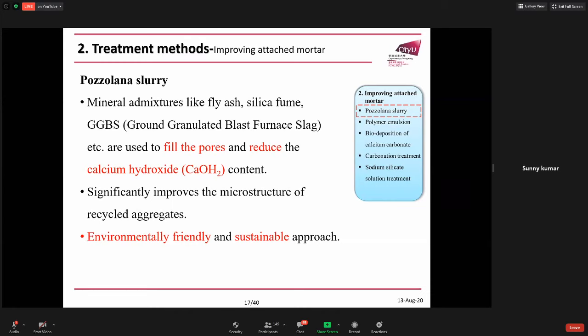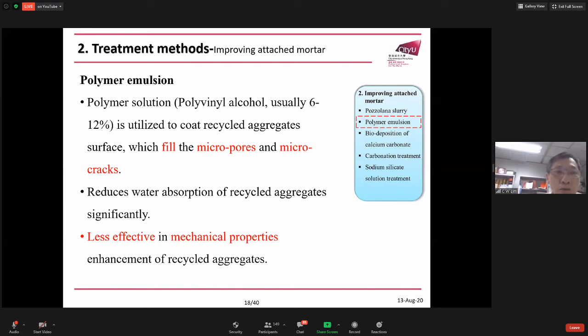The other treatment method is by improving the attached mortar. The first one is the pozzolanic slurry. Mineral admixtures like fly ash, silica fume, and GGBS are used to fill the pores and to reduce the calcium hydroxide content. It will significantly improve the microstructure of recycled aggregates. It is environment friendly and a sustainable approach. The second method is polymer emulsion. In this case, polymer emulsion solution is utilized to coat the recycled aggregate surface, which fills the micropores and micro cracks. It reduces water absorption of recycled aggregate significantly. However, it is less effective in enhancing the mechanical properties of recycled aggregates.